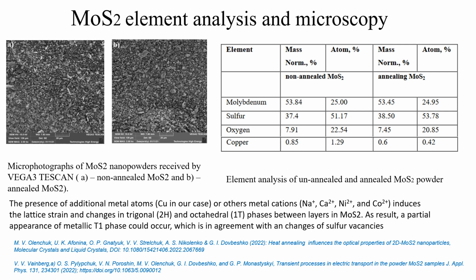Analysis of the data shows that there was no visible change in the particle morphology. The image shows that the particle size ranges from tens of microns, maybe more, to tens of nanometers. Large particles of the order of units of microns and more have a predominantly flat surface on which smaller particles are located.